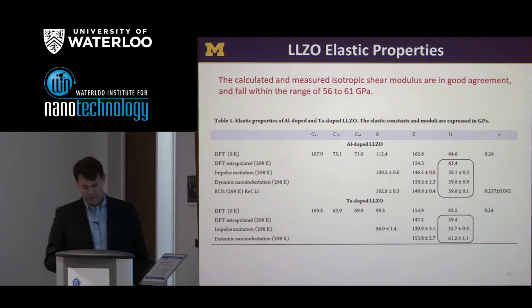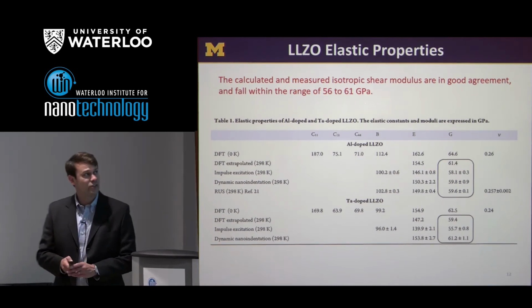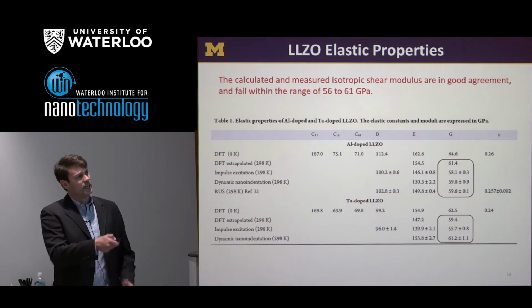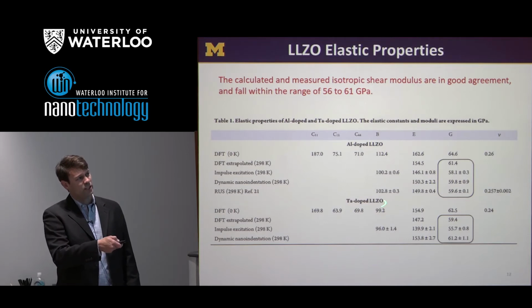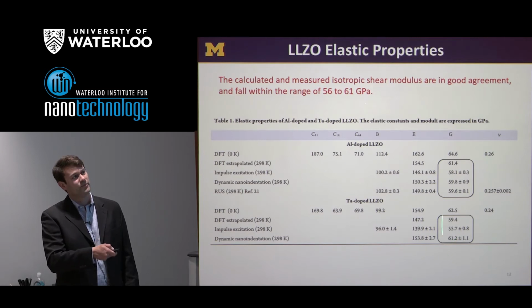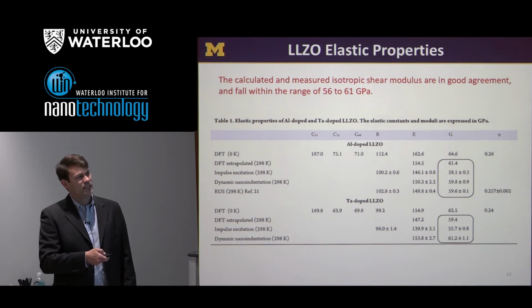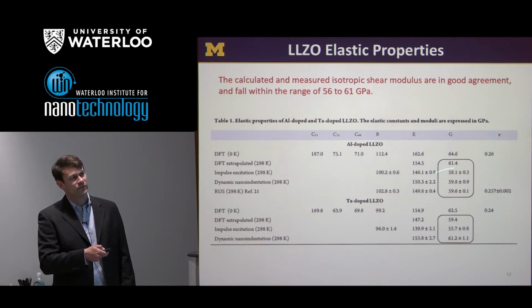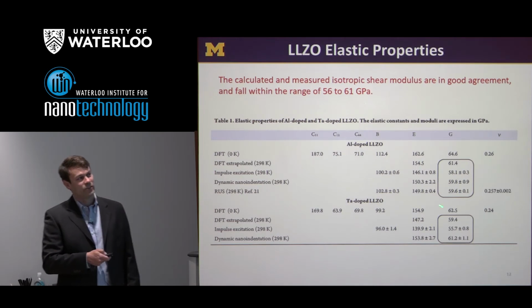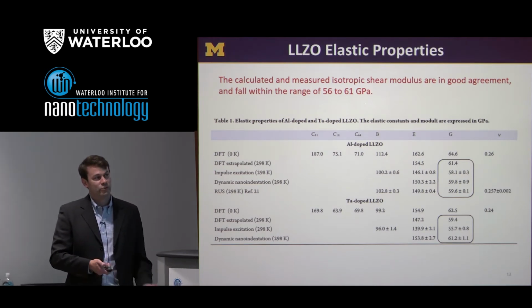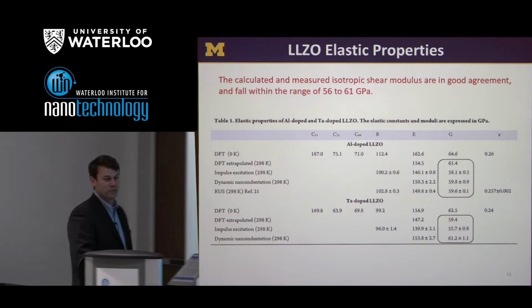And so this is a table that summarizes the comparison between the experiments and theory. So we have the aluminum doped case, the tantalum doped case, and what I want to focus on is just the shear modulus, G. So from the calculations, we're getting about 61 or 60 gigapascals, and that compares very well with the experiments. In fact, we have the impulse excitation, the nanoindentation giving us values around 58 to 60. An earlier study using ultrasound measurements gave a value of about 60. So this is really good agreement between theory and experiment.